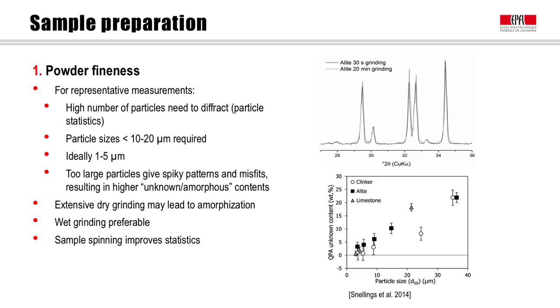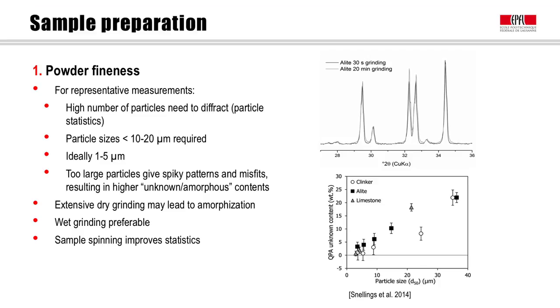This can be seen in the figure on the lower right, where, as a function of particle size, the y-axis shows the unknown or amorphous content analyzed by Rietveld analysis. Clearly, if one has large particle sizes, one is actually measuring an apparent or artificial amorphous content. This is not true amorphous content and is actually related to sample misfits or XRD pattern misfits. Just grinding the sample to the appropriate fineness will enable a much more accurate assessment of the amorphous phase level.